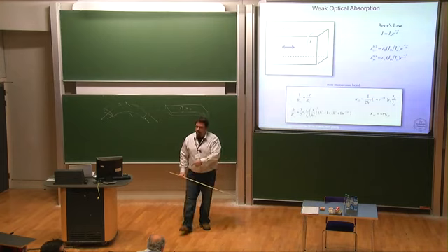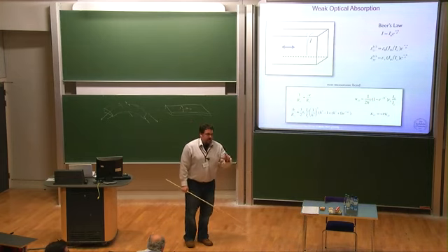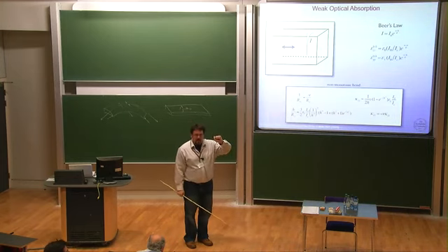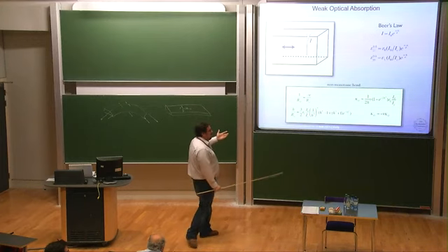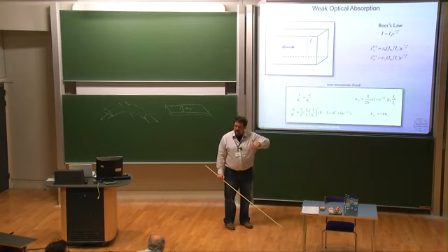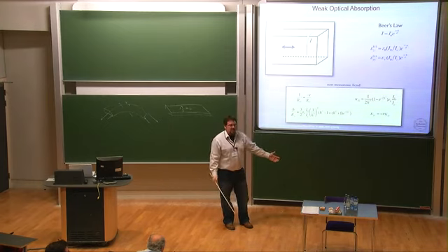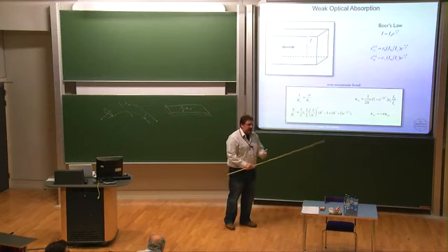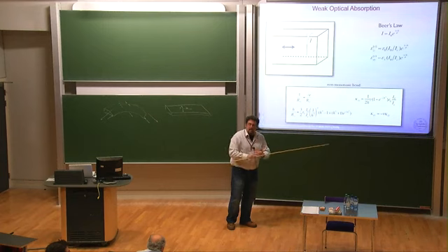In the opposite limit, when the material is very, very thin compared to the penetration depth, there's no relative gradient for the material to see. All the light just hits everything. And then because it's just a big monolithic block with no spatial variance, again, it'll flex. This time it'll elongate, but there won't be any bending.